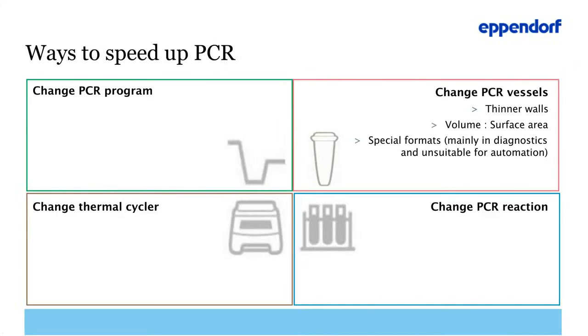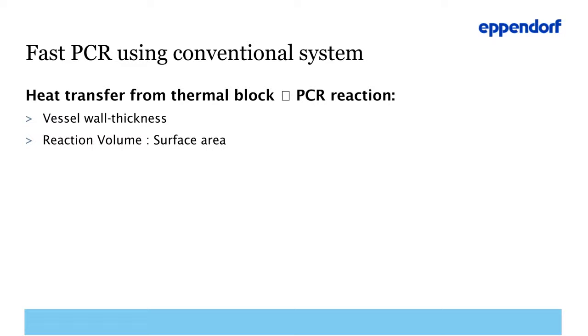Now next is to discuss the influence of PCR vessels on productivity. If cycler speed is improved by increasing temperature performance, then the improvement on PCR vessels concentrates on speeding up heat transfer, that is, from the block to the reaction. The common strategies to achieve this are to make the walls of the vessels thinner, or to increase the volume to surface area ratio that is in contact with the thermal block. The former is limited by the fragility of the polymer material, which is typically polypropylene, because polypropylene is highly malleable and hence suitable for making thin wall vessels, but precisely because it is soft, it is fragile and difficult to handle, so there is a limit to how thin one can go making it.